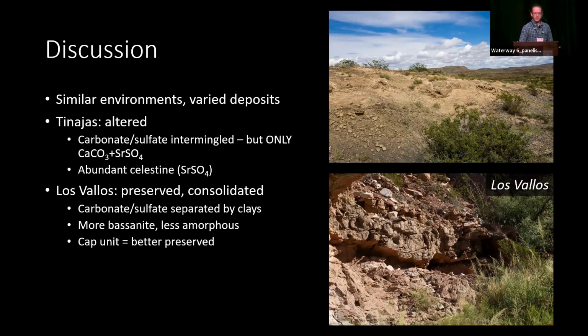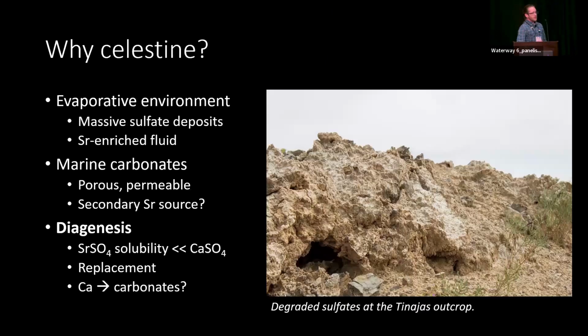So if you're like me, you saw that celestine and went, how did that get there? And we think that this is a product of diagenesis. There's a great paper by Hanor et al. in 2004 looking at large celestine deposits in places like Greenland, Germany, Italy. And they find that it's probably a diagenetic product, that you have an evaporative environment where you lay down a bunch of calcium sulfate and you get water that is having strontium concentrated in it due to evaporation and possibly due to leaching strontium out of marine carbonates that it is passing through as they supply some porosity and permeability as this water begins to infiltrate. And then you have this strontium-rich water coming into contact with calcium-rich sediments, and a replacement reaction happens because strontium sulfate is much less soluble than calcium sulfate.